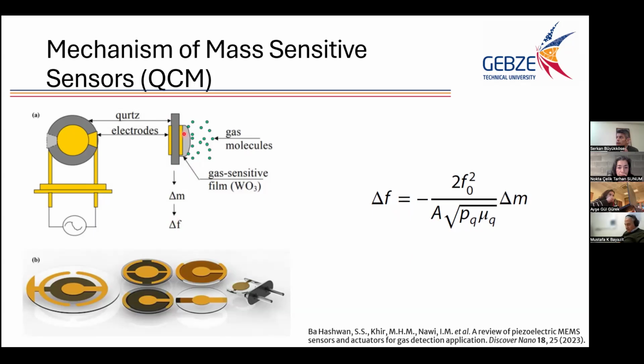If you have a sensitive layer on top of one of the electrodes, and if some gas molecules are absorbed on it, then this appears as mass loading, which is indicated here as delta M, and it appears as a shift of the resonance frequency. So here, by using this formula, you can easily calculate the thickness of the material, or you can get the sensor response by measuring the shift in resonance frequency.